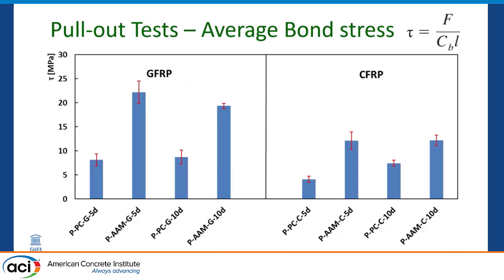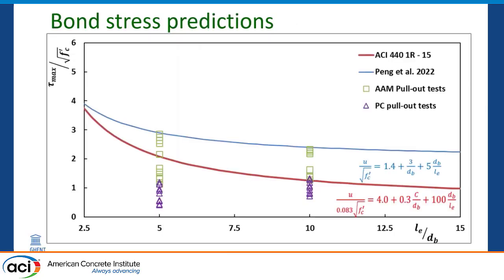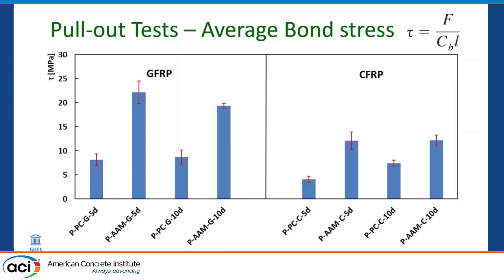Here we can see the average bond stress for the maximum load. We see that the alkali-activated material outperforms Portland cement by more than 30%. And we see that when changed from 5D to 10D, in Portland cement mixtures the average bond stress actually increased marginally, and when it comes to the alkali-activated mortar, it decreases. When it comes to the GFRP, we see also the increase in the bond stress when changed from 5D to 10D, but no increase when changed from 5D to 10D for the alkali-activated.